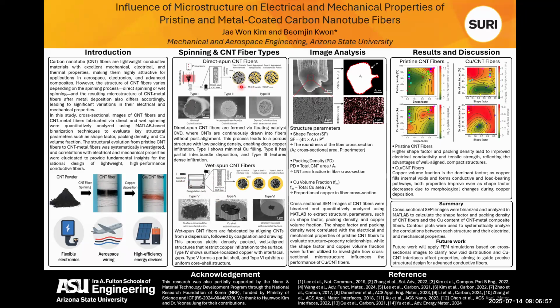Direct spun CNT fibers tend to have a loose and porous structure, allowing deeper copper infiltration. In contrast, wet spun CNT fibers are highly aligned and dense, causing copper to be mainly deposited on the surface. Based on cross-section analysis, we observed six types of copper morphologies. Type 1, Type 2, and Type 3 were found in direct spun CNT fiber, while Type 4, Type 5, and Type 6 were observed in wet spun CNT fiber.